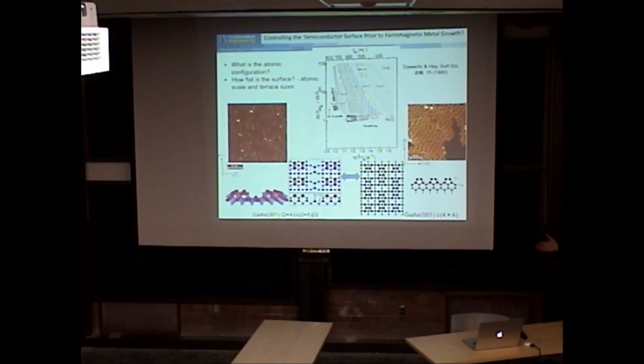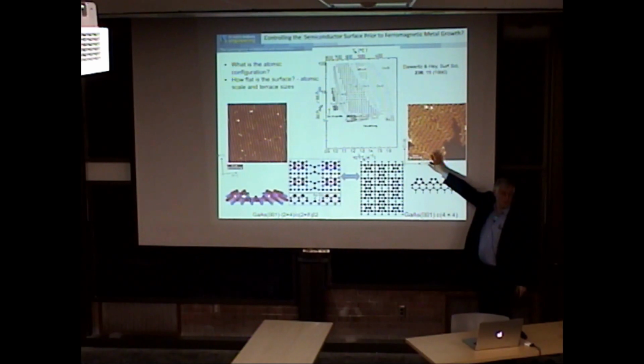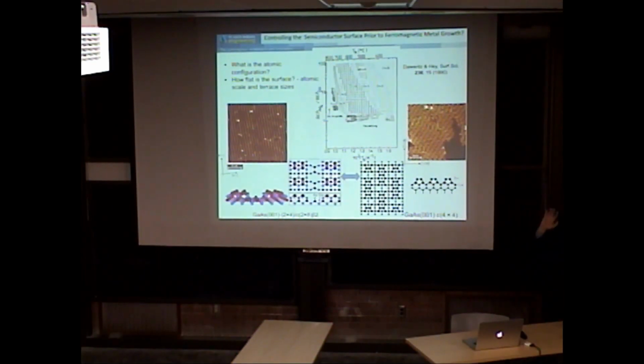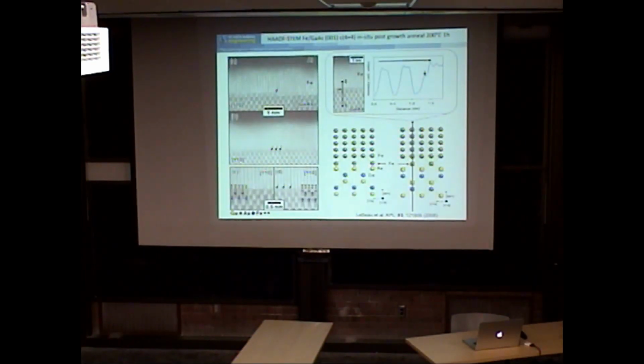You don't know, right? You don't know. So, okay, I'm going to tell you first about one we've done. This is the easiest surface to form when you've done MBE, because you just cool down a little bit in arsenic and you shut the arsenic off and take it out. All the others you have to work more to get different surface reconstructions. And I'll show you here we've actually grown iron epitaxially on top of gallium arsenide.